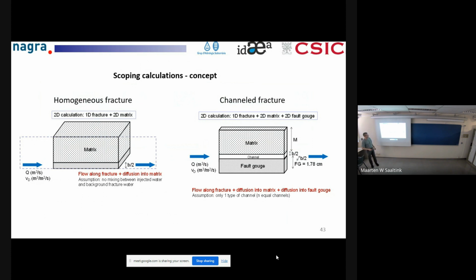Two different velocities of water. The channel is open, porosity 1, so it's an open part of the fracture. And the fault gouge has a porosity, in this case, of 0.1. The flux of water is different. The flux of water is only in the channel.